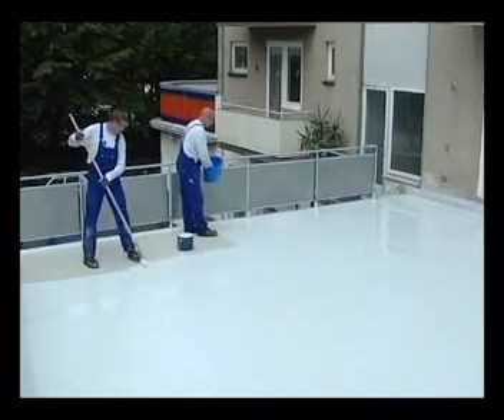KEMPEROL AC finish is matte, rapid curing, decorative, and most of all, ultraviolet resistant. The surface is rainproof at a temperature of 20 degrees Celsius after 30 minutes and can be walked on after an hour.